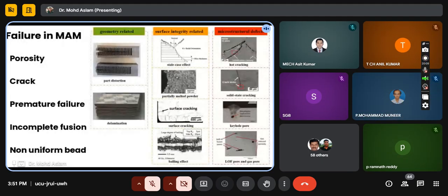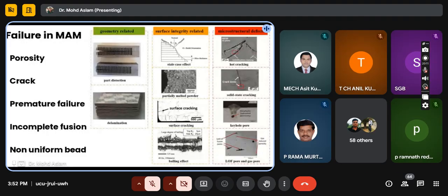Porosity: how and when is it developed? When we directly deposit any MMC powder on any metallic surface, we have observed that it produces porosity, micro holes as well as macro holes. For example, when silicon carbide is deposited on a mild steel substrate, it will develop porosity as well as micro holes.